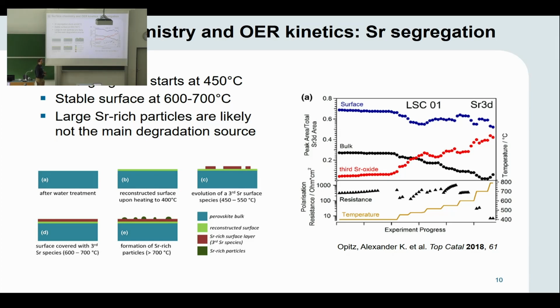At higher temperature, the degradation rate slows down, most probably because the surface is reaching an equilibrium state. And also, these strontium-rich large particles are most likely not the main degradation source because they do not cover the entire surface area. They just do not look so nice.